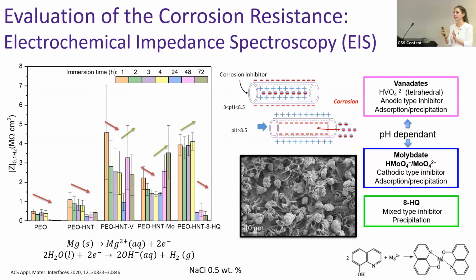Right now, one of the reasons why I selected halloysite nanotubes is because the pKa of the nanotubes matches that of the pH variations that we would observe in magnesium. So I'm quite happy with how the nanotubes respond to pH. That's why I selected it. We could change the range at which the inhibitors are released if we functionalize it with further functional groups like amines. So this is a possibility, but right now we don't really need it with halloysite nanotubes, although it could be necessary with other types of nanocontainers such as fibrous silica to match the pH trigger that we need to that of the capacity to host it inside the nanotube.